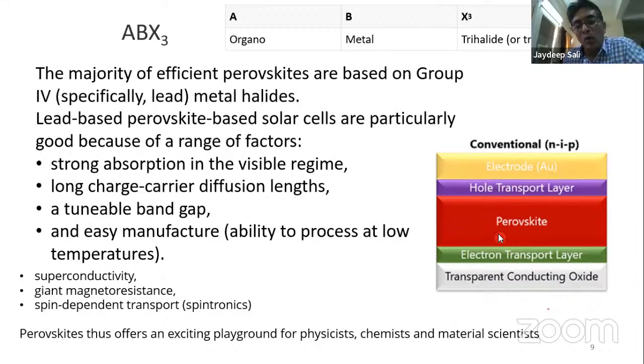So they must have a long diffusion length, so that they reach the hole transport layer or electron transport layer without recombination. Therefore, a perovskite material having a long charge carrier diffusion length is desired, and lead-based perovskite materials have this property. Thirdly, by changing its configuration by doping, you can tune the band gap, so we have a tunable band gap. And last and most important is the ability to synthesize thin films for solar cells at low temperature with a solution processable technology. So it has easy manufacturing capability.